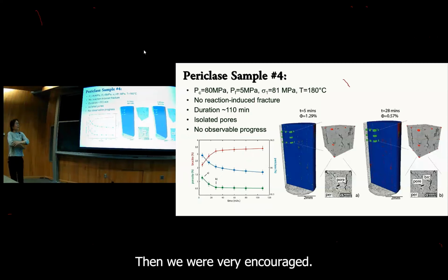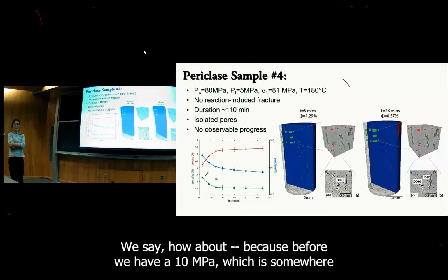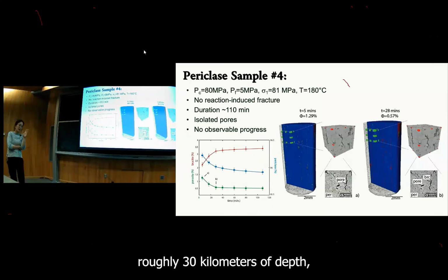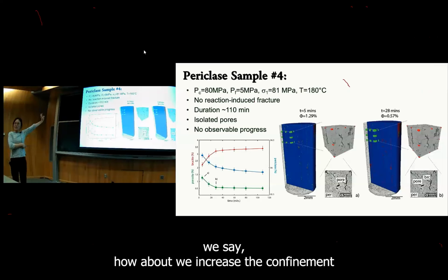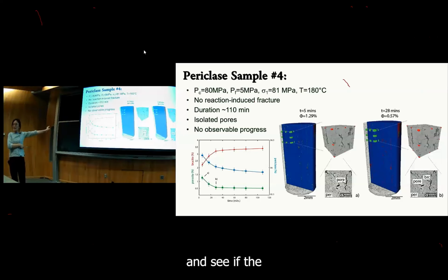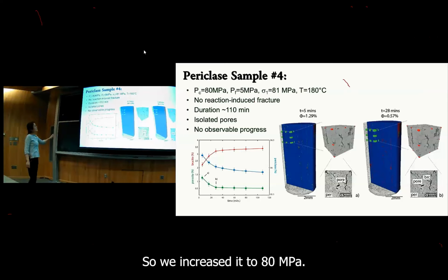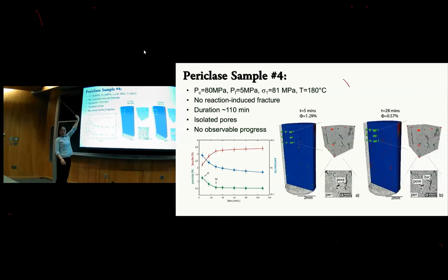Then we were very encouraged. We said, how about, because before we had it at 10 MPa, which is roughly 30 kilometers depth, how about we increase the confinement and see if this transformation can break the rock again. So we increased it to 80 MPa.